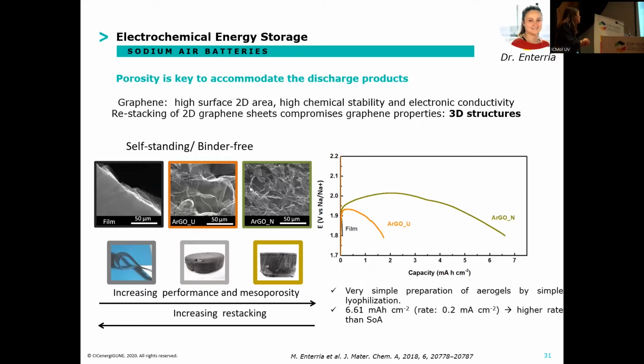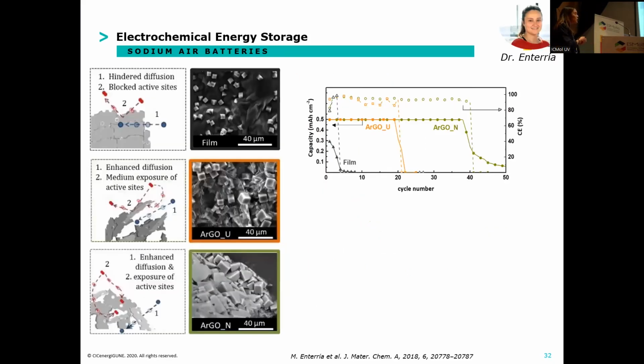Why? Because when we have a film, the diffusion of oxygen is hindered. So we just have the diffusion on top of the cathode surface, where the reactions are going to happen. But when we increase the mesoporosity, we have the diffusion of oxygen that can go into the graphene sheets, and the oxygen reduction can happen in those sheets. And that is enhanced for the one with higher mesoporosity.